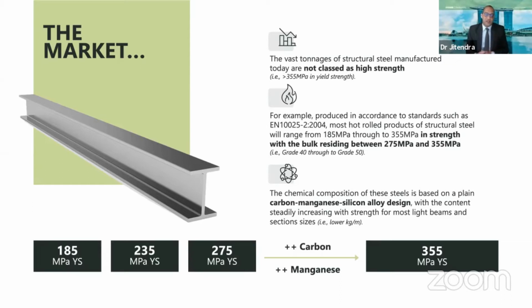In order to make these higher strength steels from 185 strengths upwards, and particularly 275 and 355, the base composition of these steels is carbon, manganese, and silicon, silicon mainly being through the steelmaking process routes. To make these higher strength steels, steelmakers would generally adopt a policy of adding either higher carbon, but most of these steels are around 0.18% carbon, and therefore go down the path of ever-increasing manganese content. Typically for 185 megapascal steels, we'll see manganese content at very low levels, about 0.4 to 0.6. As we progress to 355, that manganese level will gradually increase significantly, in some cases to levels of about 1.2, 1.4.